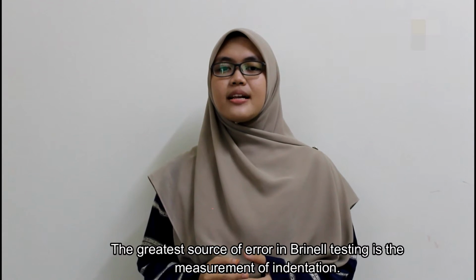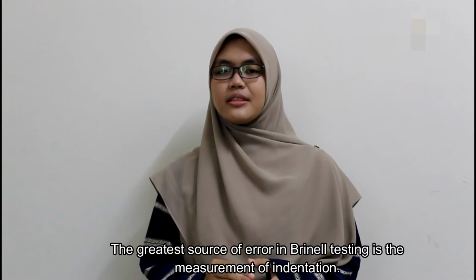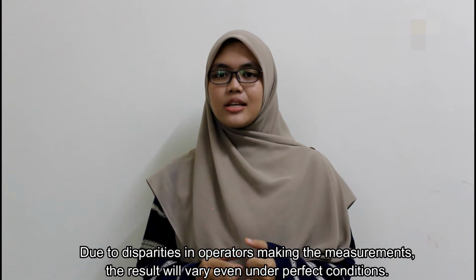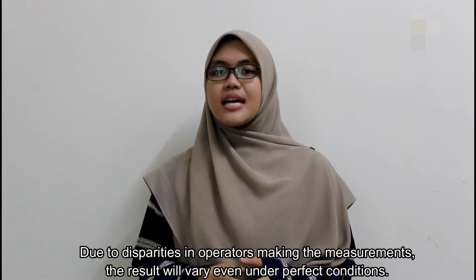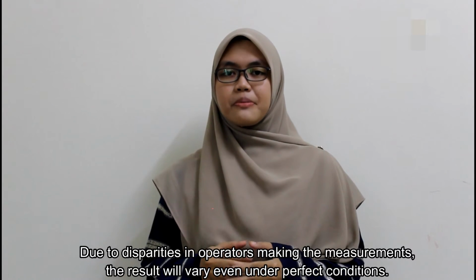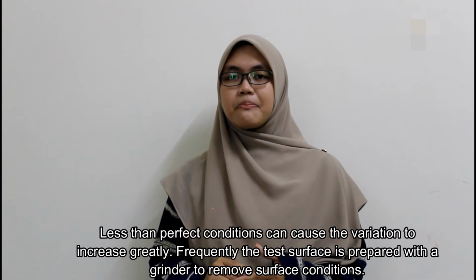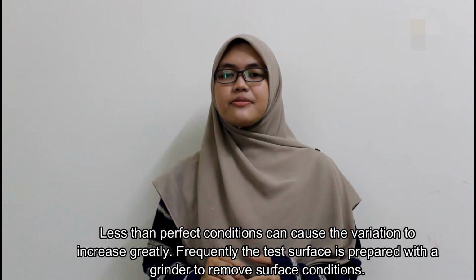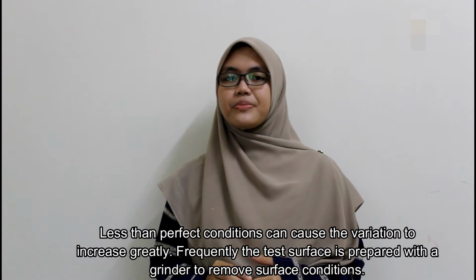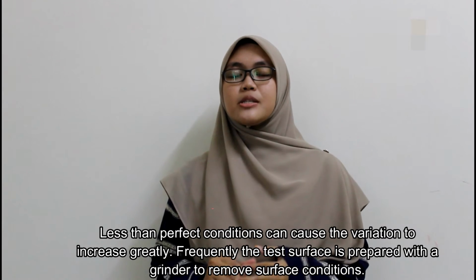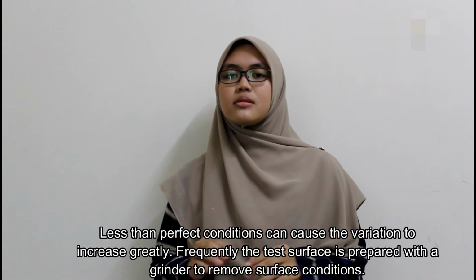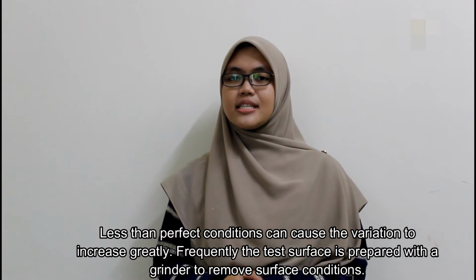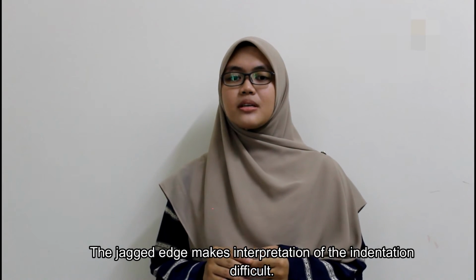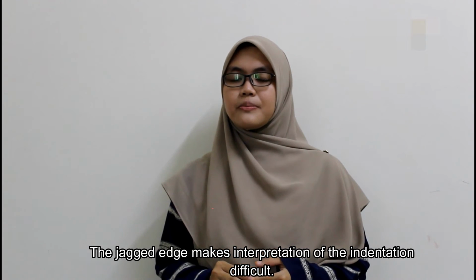The next is the error in Brinell testing. The greatest source of error in Brinell testing is the measurement of the indentation. Due to disparities in operators making the measurements, the result will vary even under perfect conditions. Less than perfect conditions can cause the variation to increase greatly. Frequently, the test surface is prepared with a grinder to remove surface conditions. The jagged edge makes interpretation of the indentation difficult.